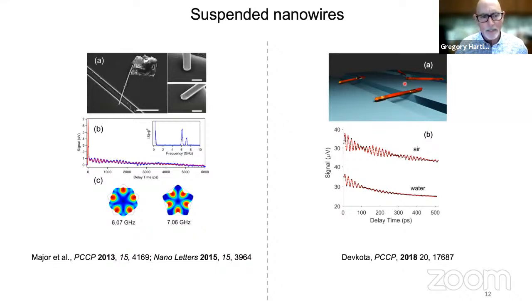rid of the substrate. So these are some examples of some nanowires where we've made substrates where we've cut little trenches in them and then just dropped some nanowires onto that substrate, and some of them end up hanging over the trenches. And then if we look in the region over the trench, we have a material that's not going to lose its energy by radiating sound waves, because there's nothing to radiate the sound waves to, right? It's just air.